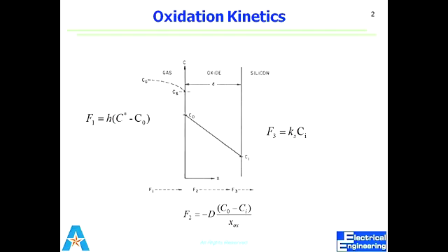On the glass slide you can deposit the oxide layer, but you cannot grow it, because growth means that oxygen and silicon react with each other and form silicon dioxide. Chemically they react together, and we say that oxide is being grown. So for thermal growth of oxide, we need a silicon substrate.